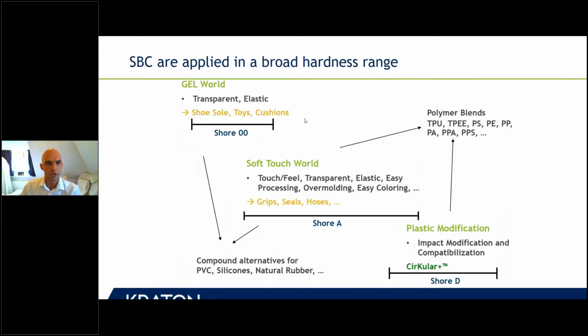Just briefly, how are styrenic block polymers applied? It's a pretty broad range of hardnesses. You start with Shore 00, and that's more like the gel world: shoe soles, toys, cushions, etc. Even diblocks are used in oil modification and in cosmetics, for instance. Triblocks are also used in cosmetics, by the way, for instance as depilatory waxes, because they give some strength to a wax, and you have more cohesive strength through the triblock network.